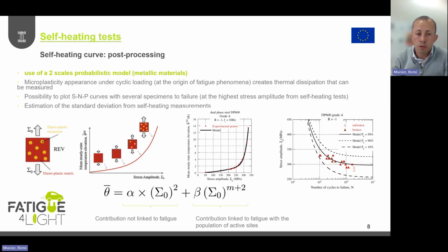So the evolution of the temperature of the specimen can be decomposed in two contributions. One is not linked to fatigue properties, which is the first one at low stress amplitude, and one is directly linked to the evolution of microplasticity inside the volume. And then after that, with the model, and as Sergi said, with the weakest link theory, we can plot complete S-N curves according to the mean evolution of the fatigue, and then the standard deviation.